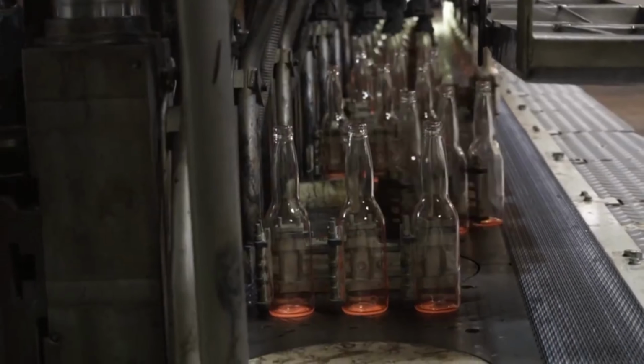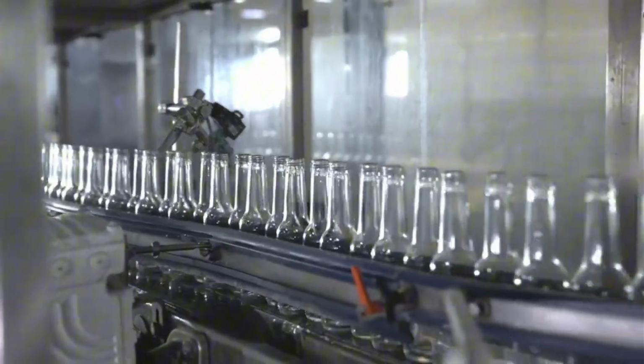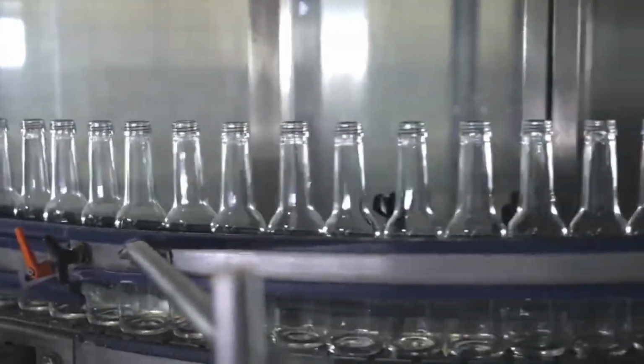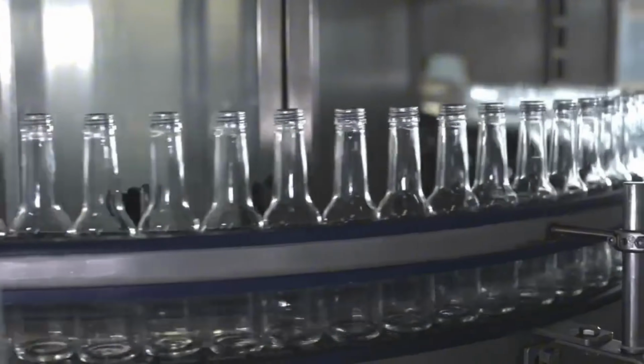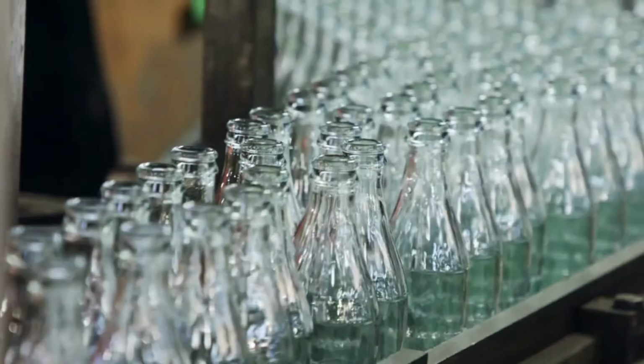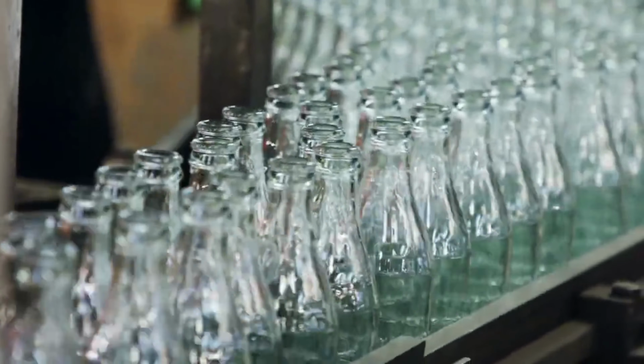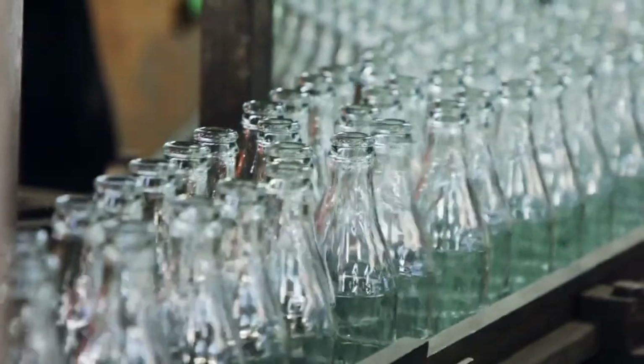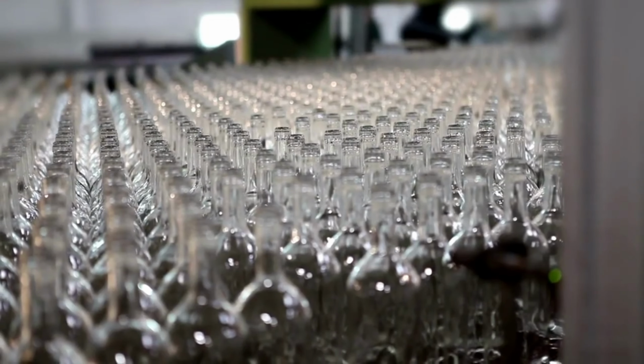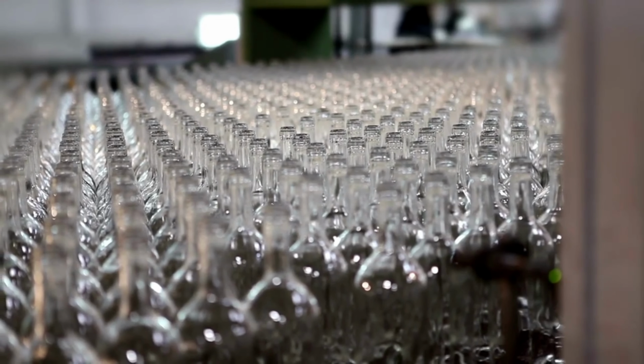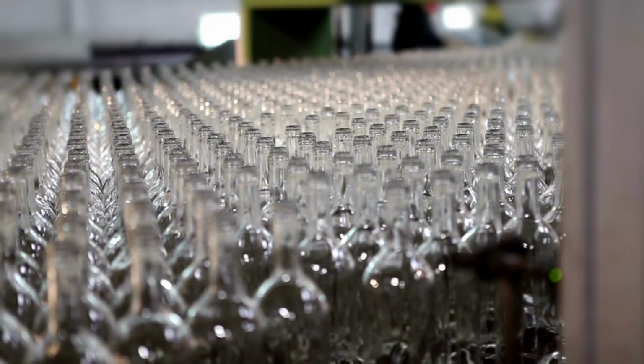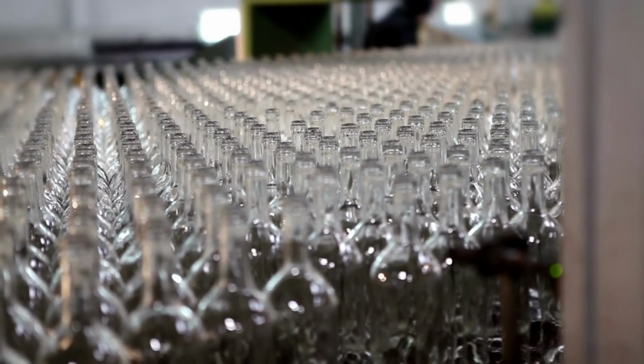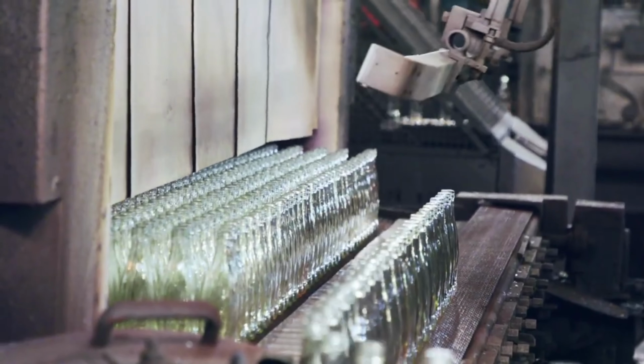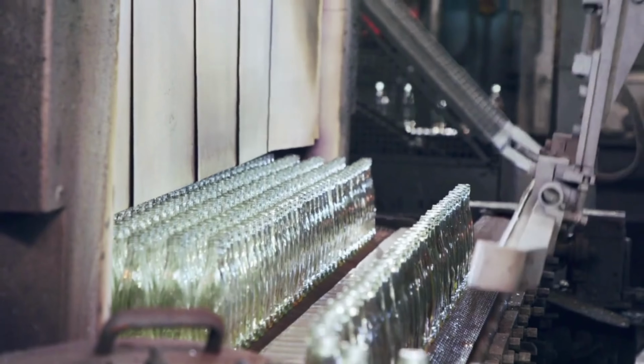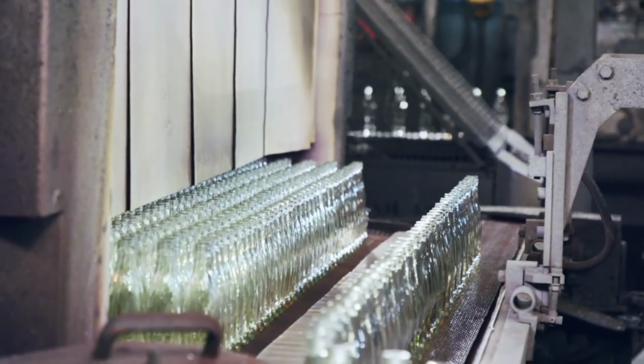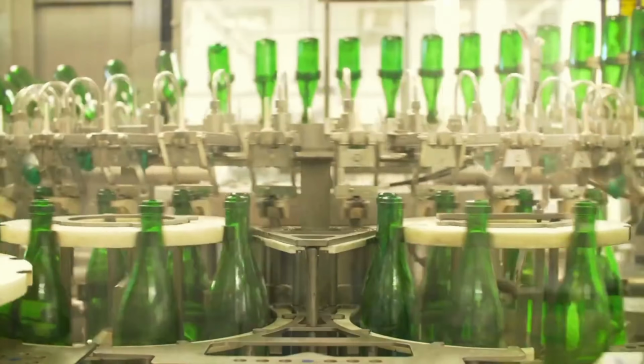Once shaped, the newborn bottles are carried by conveyor through a Lehr, an annealing oven designed not to heat the bottles but to cool them gradually, because rapid cooling would introduce internal stress that might not show visibly but could cause explosive breakage later. And so the Lehr slowly steps the temperature down over 30 minutes to an hour, ensuring the structural stability of each bottle. And as they exit, the bottles no longer glow red.